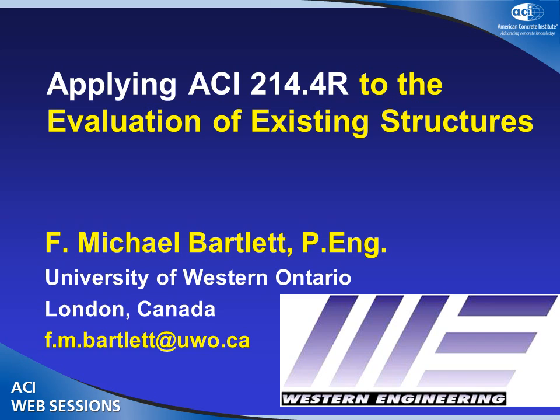It was cored when the bridge was being considered for rehabilitation in the 1970s, and the 3,000 psi concrete had turned into somewhere between 6,000 and 8,000 psi concrete. So particularly for older coarse ground cements, if you've got a nice condition where hydration can keep on happening, using a number as an in-place strength that you've taken off a specification or a drawing somewhere would be very conservative, and that's really where I'm coming from.